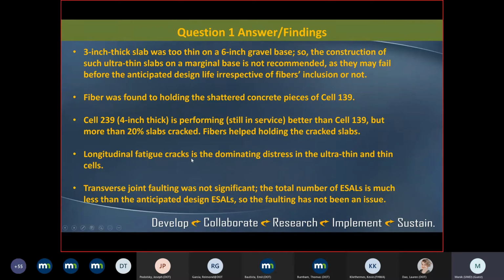And then the longitudinal cracks in the wheel path are the dominating distress, and it makes sense because the structure is very thin, so the distresses are right under the wheel path because the load stresses in very thin concrete are really high. Joint faulting, as we saw, was not an issue so far because we saw the cracks earlier, and the total number of ESALs on cells 139 and 239 was far less than probably the anticipated design ESALs. So we did not see any faulting. Faulting takes some time to occur, I mean, time or traffic load repetitions.